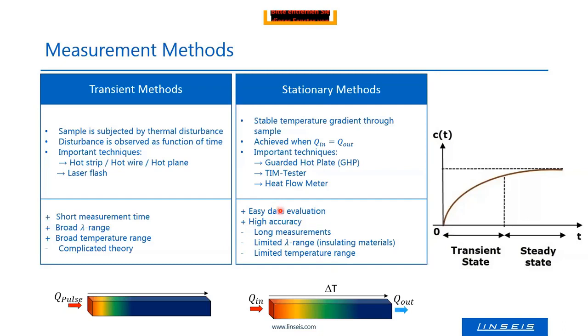Stationary or steady state methods are very accurate. The thermal conductivity can be measured within 1 or 2% uncertainty. The disadvantage of this method is that the measurement takes a long time. You have to wait until you have a constant delta T, and depending on the samples, it can take hours or, for very low conductors, even some days. The temperature range is limited. That's a disadvantage. And also the lambda range, the range for the thermal conductivity, is limited.